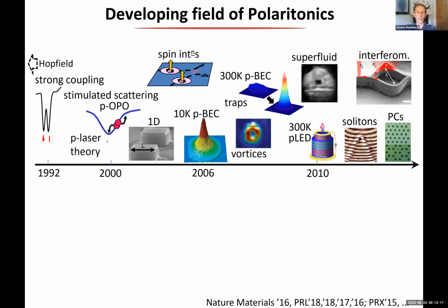What I actually managed to do the first was realize that the nonlinear properties of this system are astounding. So if you inject polaritons onto this dispersion at a particular point on the dispersion here, it allows these nonlinear interactions to take place. And in fact, they're enormously enhanced by the stimulated scattering, by the bosonic nature. So that was the first inkling that you should be able to do all sorts of interesting bosonic things with this system. And then that lasted, and people started to see indeed condensates in the mid-2000s.